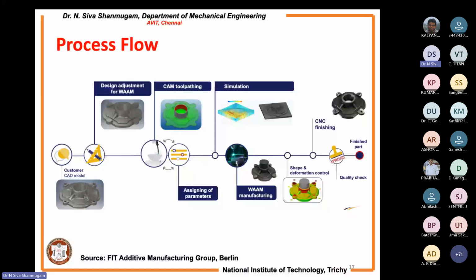And as I mentioned here, this is the process flow, a beautiful process flow. It is applicable for all manufacturing processes. It starts with the CAD model; orient the CAD model according to WAAM, because you have to do the final finish of the component. For that, you have to give a cushion effect. If the thickness is 1 mm, you increase it to 1.2 mm; 0.2 mm of material should be machined to get the finish of the component. Then do the design adjustment for WAAM, do the CAM path tooling, that is, find out the G codes and M codes for how to deposit the material, and assign the process parameters. Do subsequent simulations to find out the effect of process parameters. As I mentioned earlier, the residual stresses, how the stresses are induced in the body, what about the temperature, whether it is reaching 2000 degrees or less than 1500; you can do all the finite element simulation and then do the WAAM manufacturing.